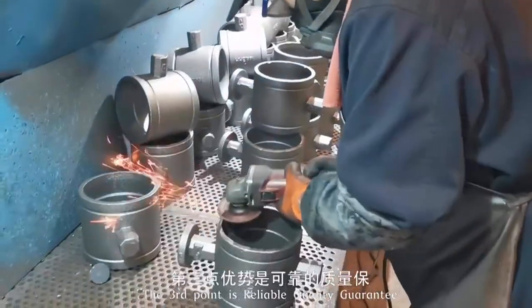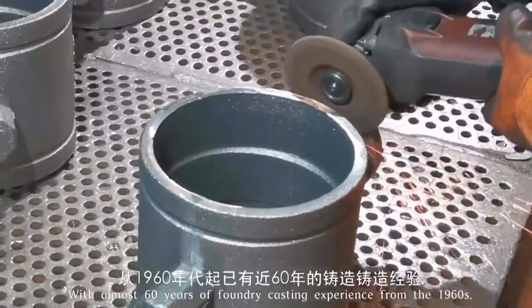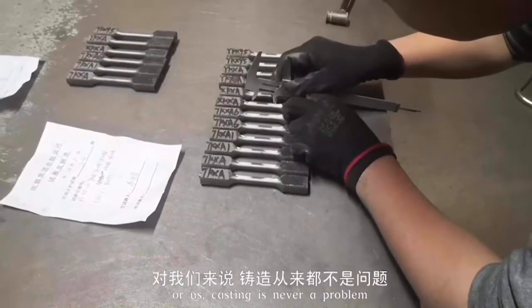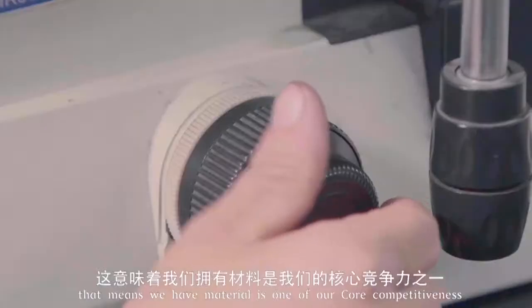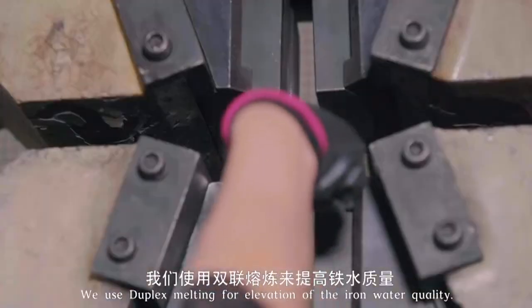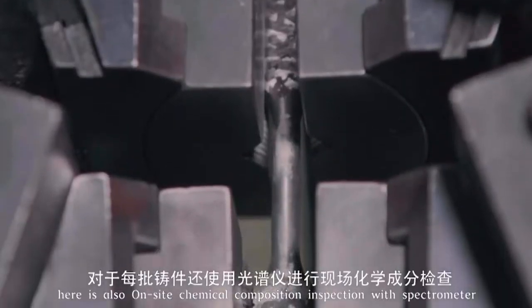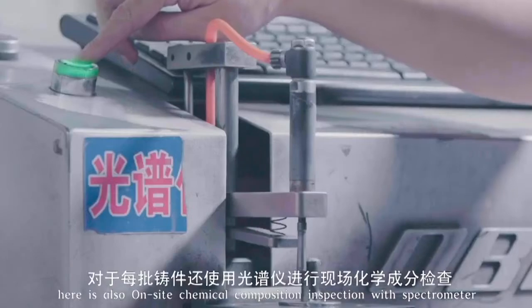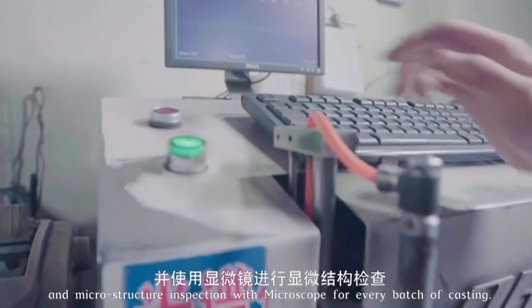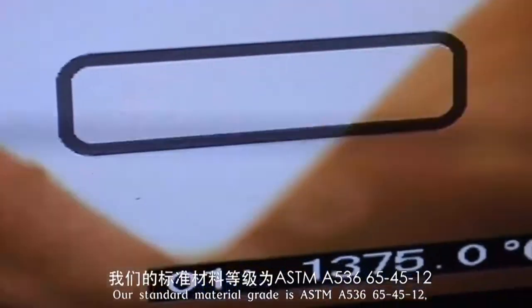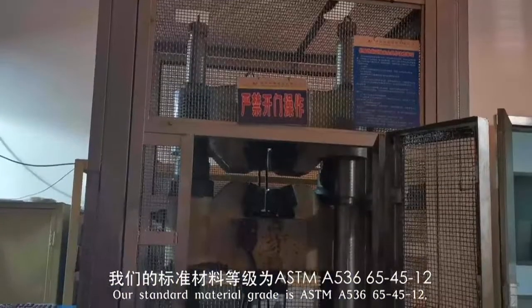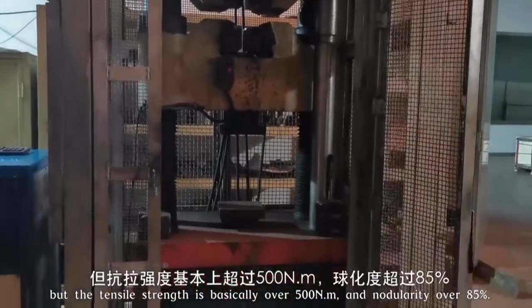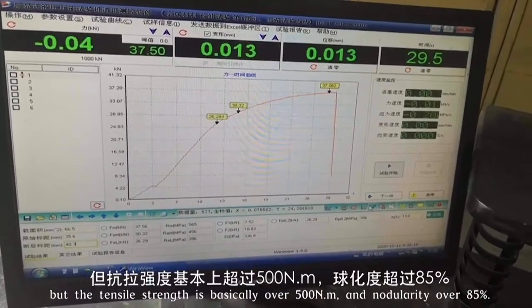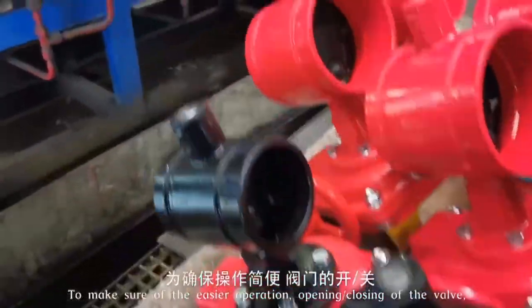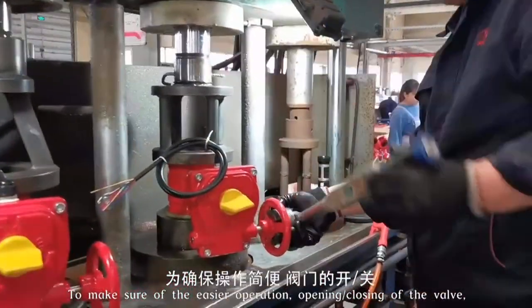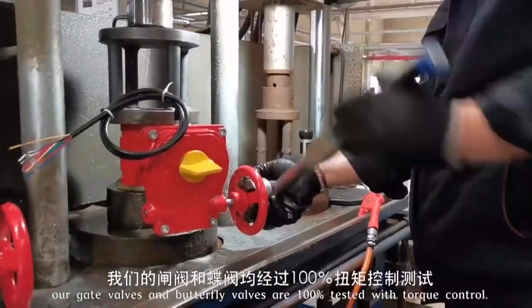The third point is reliable quality guarantee. With almost 60 years of foundry casting experience from the 1960s, casting is never a problem for us. That means material is one of our core competitiveness. We use duplex melting for improving the iron water quality. There is also on-site chemical composition inspection with a spectrometer and microstructure inspection with a microscope for every batch of casting. Our standard material grade is ASTM A536 65-45-12, but the tensile strength is basically over 500 N/mm² and nodularity over 85%. To make sure of easier operation, opening or closing of the valve, our gate valves and butterfly valves are 100% tested with torque control.